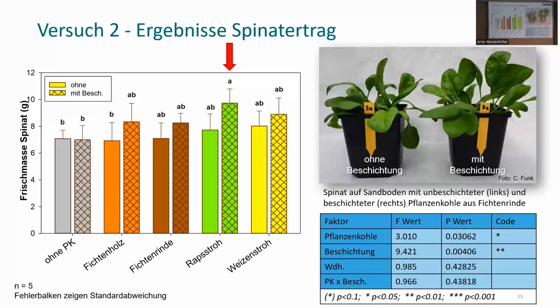And what you also see here is that coating doesn't have an impact on the yield alone. It needs to be a combination of coating and biochar that leads to a yield increase, because coated sand alone didn't yield a yield increase. And if you look at the yield, the coating is clearly a more important factor than the type of biochar you use.